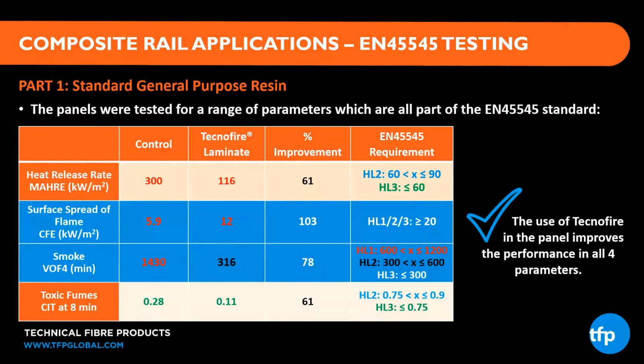fire event. If we look at the requirements, these hazard levels to EN 45545, HL2, the mid-level, which we believe is going to cover about 60 to 70, 80% of trains, the MAHRE requirement is less than 90. We're at 116. We're not quite there, but a significant improvement from 300. And we're confident that through inclusion of a small level of a secondary fire retardant technology or additive would get us over the line for HL2. And this is the systems approach that Scott alluded to in his presentation.